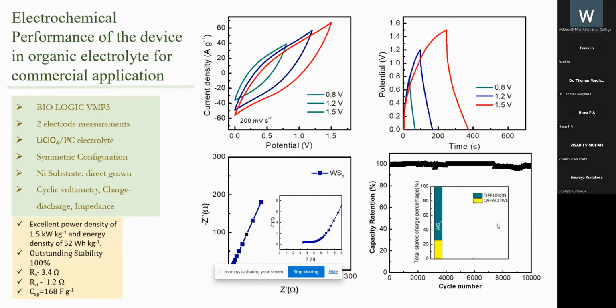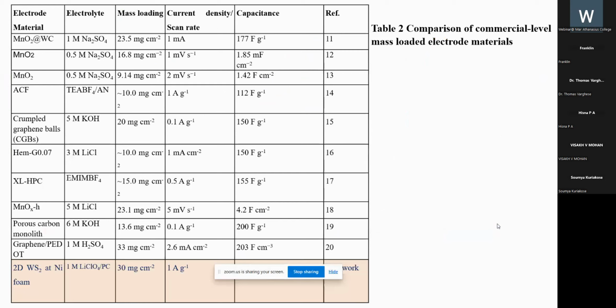There is not much difference in peaks, in both shapes and characteristics, which ensures the stability of the material. The impedance spectroscopy also shows the Rs value is 3.4 ohm and the Rct value is only 1.2 ohm, and the capacitance has reduced to 168 farad per gram. Actually, this is the highest reported value of WS2 material in organic electrolytes, and not only for WS2, but also compared to other materials. This is the highest reported value at 30 mg high mass loading condition. Compared with previous commercially mass loaded devices, we are on top.